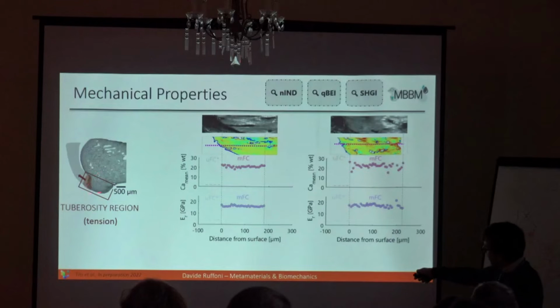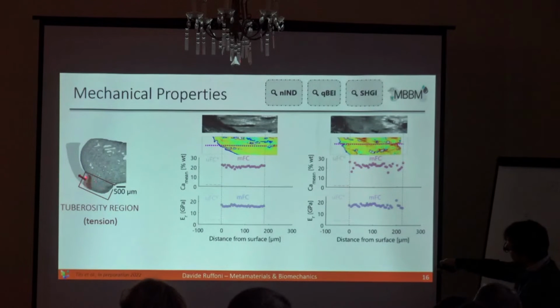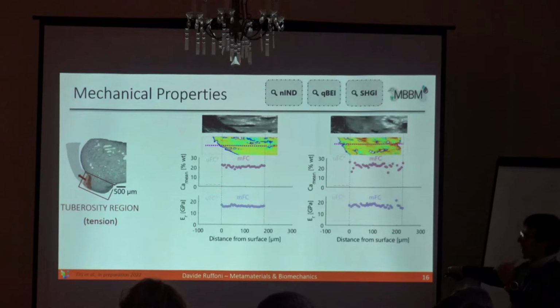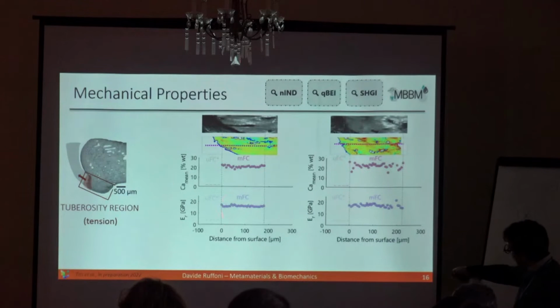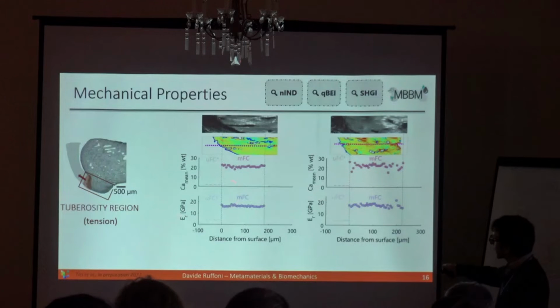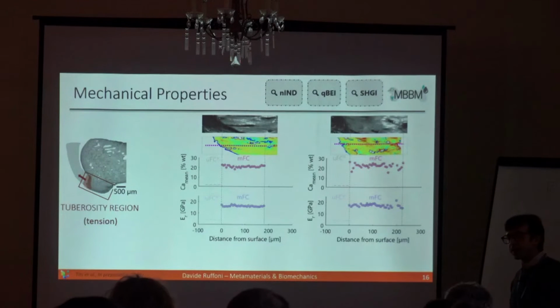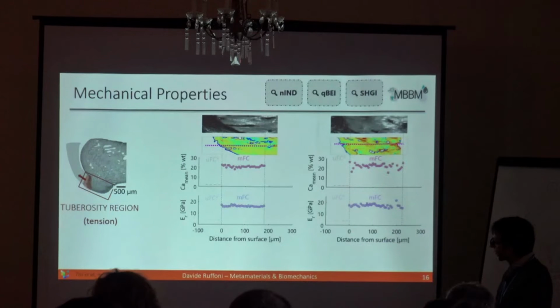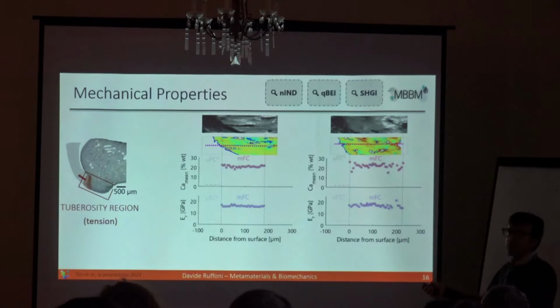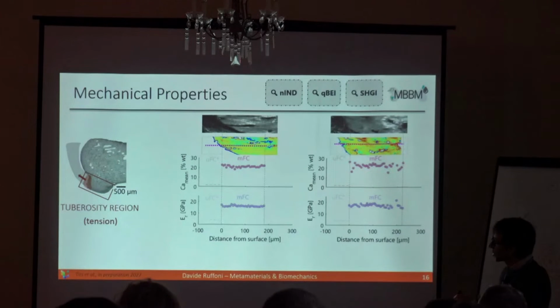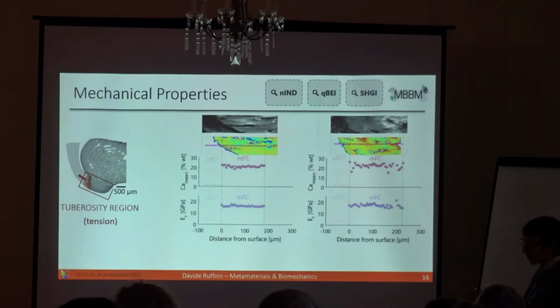What is interesting is that when we do the same measurement at the enthesis where the tendon is inserting, we basically see no gradient in mineral content. All the bone is already fully mineralized. This is reflected in the tissue modulus, which already reaches 20 gigapascal, the maximum that we observed there. So we do not really see a lot of gradients here, which was a little bit unexpected, but we see that all the tissue is highly oriented, highly stiff, and ready to take the load coming from the tendon. We assume this is done to increase the strength of the interface, to really align all the fibers to take up the load from the tendon.